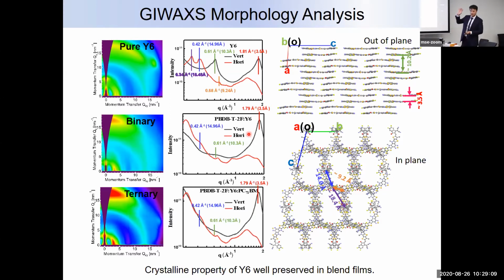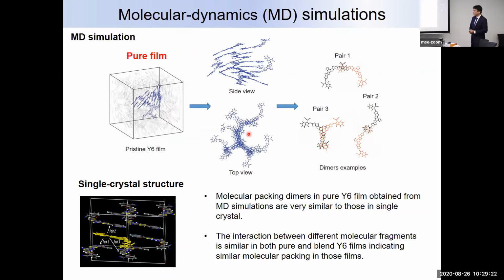So that's why I think whatever properties we find from the DFT calculation can also be carried over into this blend film. So we did a collaboration with Professor John Lupton's group for doing a more detailed molecular dynamics simulation. We just heat up the whole system to 800K, and then let it cool down slowly. It takes a couple of months to do that, right? What we find out is that this Y6 molecule has a 3-mole packing, 3 dimers. Actually, all of these packing motifs can correlate to the single crystal structure. So at least our collaborator told us that they have never seen anything like this before for other acceptors, which means this molecule has a very strong stacking. Okay, so their packing is very close to the crystal structure.